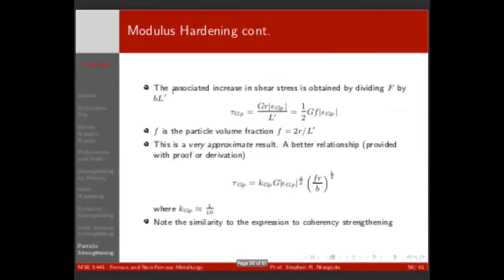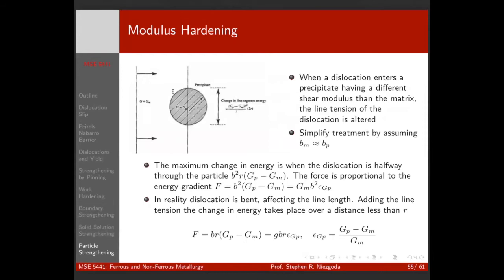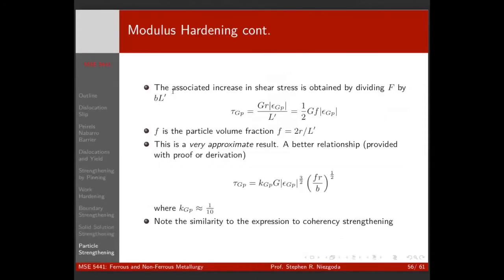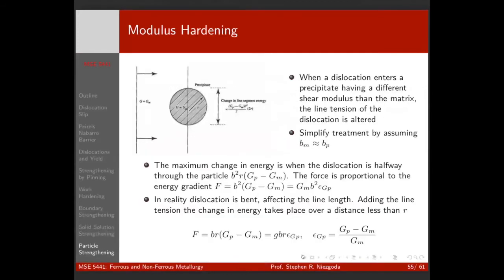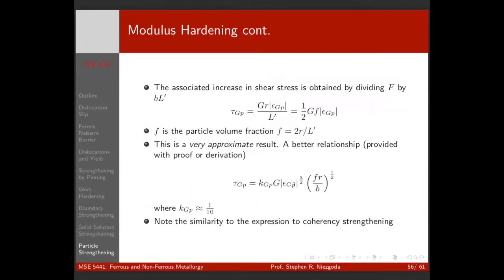And again, here for reference, and you can go through it in the reading, are some details of the magnitude, right? And again, all these follow the same sort of thing in the reading. There's this dimensionless parameter which is like a strain. It's a strain-like dimensionless term. It's not really a strain because it has nothing to do with the displacements of atoms, but in terms of energetic calculations, you would use it in place of strain. But it's always a dimensionless parameter that gives you a difference. So in this case, it's the normalized difference between the shear modulus of the particle and the matrix, right? And typically you're going to be proportional to that to some power. In this case, it's the 3/2 power.